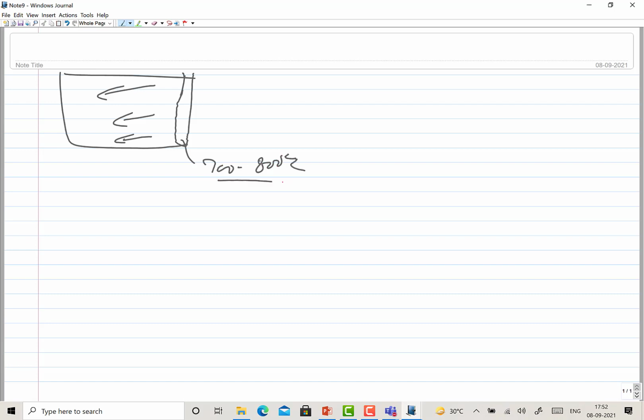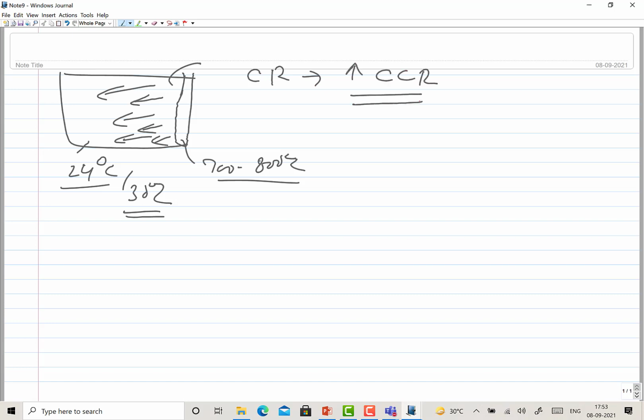So these are the good things. Whatever changes are taking place in similar metal joining, it is the same. Hardening, softening, HAZ or upsetting, all are the same or equal on both sides. But still, you have a large mass of metal behind the interface, which is being heated to a temperature of 700 or 800 degrees centigrade, and below that you have base metal temperature of 25 or 30 degrees centigrade. So this will be extracting or sucking the heat very rapidly, transferring the heat from the interface very rapidly, and that is why the cooling rates experienced are in general usually greater than a critical cooling rate, especially for hardenable steels.